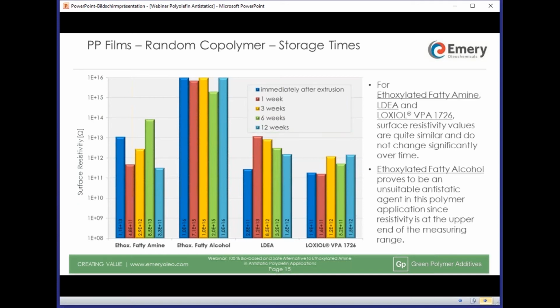Results. Ethoxylated fatty amine, LDEA and LOXIOL VPA 1726 provide an overall similar antistatic performance. There are some ups and downs, but there is neither a significant difference between those three nor a trend. Additive migration is obviously quite quick in these thin films, so the performance is there right after extrusion without waiting for the additive to migrate.